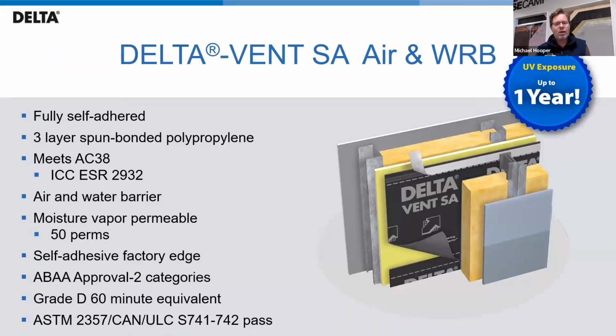Which brings us to what goes behind the Delta Dry, and this is our new and improved Delta Vent SA product. And this is a sheet applied membrane, self-adhered, and we use a unique 3-layer spun bonded polypropylene composite product. And we use a thermal polyurethane vapor permeable performance layer in between. This has been tested to AC 38. It's very effective, and it does have fairly high permeability. So dry cup is 30 perms, wet cup 50 perms.